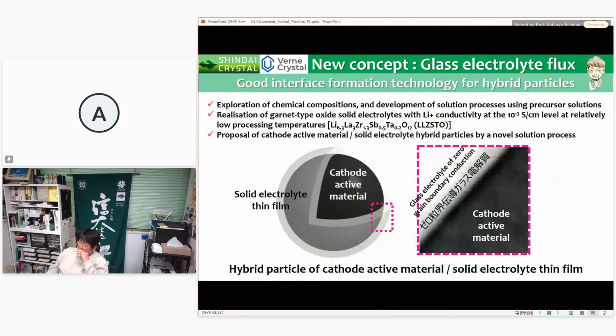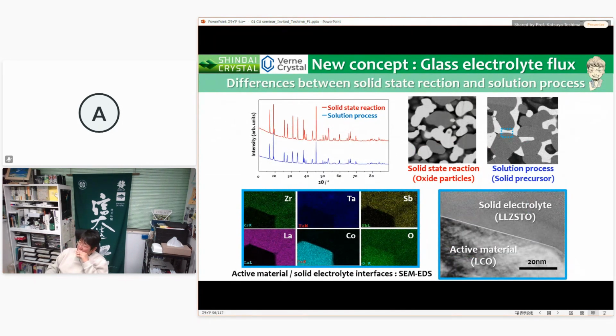Recently, we have fabricated unique materials in which the active material is covered by a very uniform solid electrolyte thin film. We call this zero grain boundary conductive glass electrolyte. As shown in these figures - XRD, SEM, TEM, and EDS - they are very well combined.